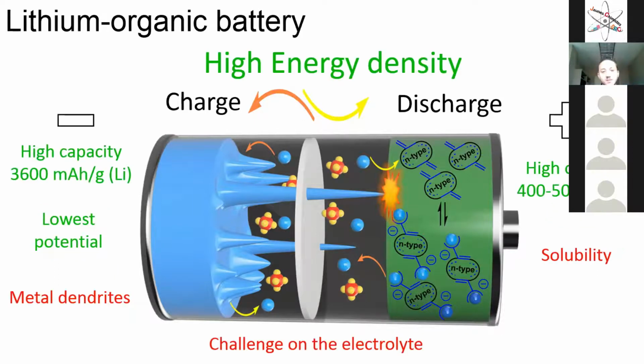The most famous example here is lithium metal. Why? Because lithium is the lightest element, so it gives a high capacity. Here we are talking about 3,600 milliampere hour per gram, and it provides the lowest potential. On the other hand, we have organic materials that can provide high capacity up to 500 milliampere hour per gram. So if you combine an organic cathode material with a lithium metal anode, you are talking about high energy density. So it's very, very promising, but it's very, very challenging.